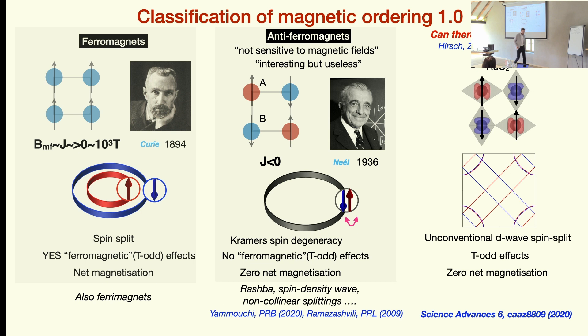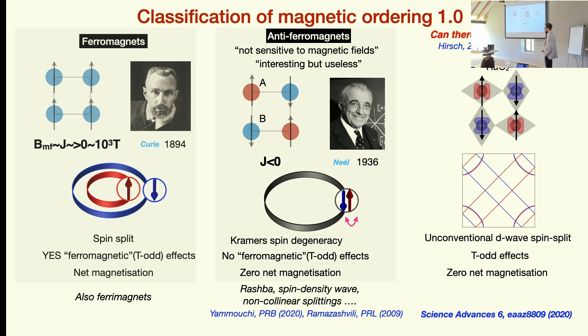What is interesting about ruthenium dioxide is that in certain aspects it behaves as an antiferromagnet — the quantization axis of the spin densities is perfectly compensated — but in other aspects it behaves somewhat like a ferromagnet because you have spin splitting in the band structure. In yet other aspects it is neither, it's unconventional. One of these unconventional features is this anisotropic magnetization density; another is that even though you have spin splitting, because of this D-wave rotational symmetry, it is perfectly compensated. The question is: how shall we understand this? Is it just some outlier, a unique black-swan material, or is something more general going on?